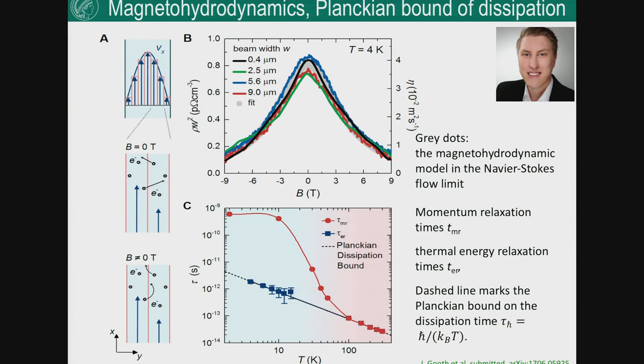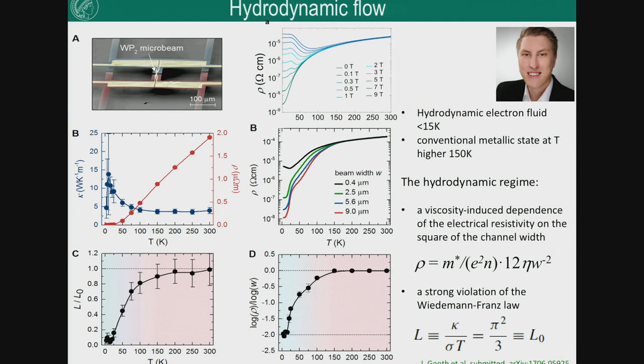And then the third question, which was not investigated up to now, came simply when I saw this behavior. Depending on the size, here's your resistivity as a function of temperature, and with smaller size the resistance becomes much larger. This is like what you observe also in a magnetic field. In 9 Tesla, here's the upper curve, if you did not know that this is 9 Tesla, it looks like a topological insulator. And this is a typical curve for every Dirac and Weyl semi-metal, okay? So if you apply a magnetic field, it looks like a topological insulator, with a plateau at the end.